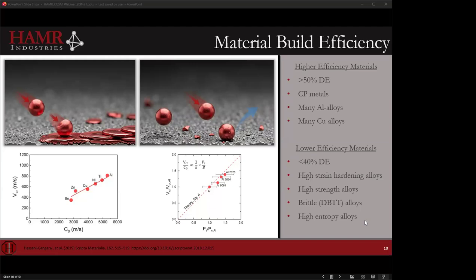These are really high strain hardening alloys. You can imagine as that particle tries to deform, it's going to be a challenge. High strength alloys, brittle alloys, so things that are brittle at low temperature. Cold spray is not a very high temperature process. The particles don't stay that warm for that long. And high temperature alloys, or high entropy alloys, excuse me, tend to have very high spall strengths, so they tend to be a little more challenging to deposit.